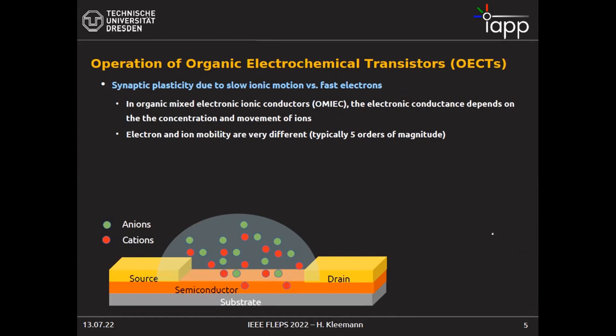We have the normal elements of a source and drain electrode. We have a semiconductor material — usually a polymer material that swells when you dip it into water or solvent — and the semiconductor is able to transport ions as well as electrons and holes. If you put a droplet of electrolyte or water with NaCl, for example, on top, ions can penetrate into the semiconductor.